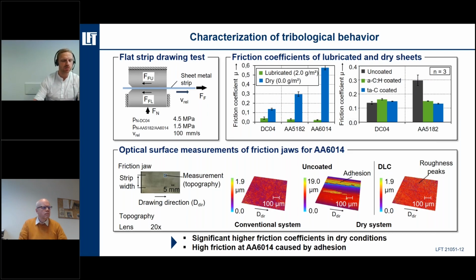we did some tribological tests in order to analyze the tribological performance of lubricated and unlubricated material compositions. For the characterization of the tribological behavior, the flat strip drawing test is commonly used to determine friction coefficients for deep drawing processes. Here in the upper left corner, you can see the basic principle of the applied test setup. The sheet metal, the blue line, which you can see here, is placed between two friction jaws. The lower jaw is moving upwards, applied with a defined normal force. While the strip is drawn through the jaws, a distinct drawing velocity was set up, and the resulting friction force could be measured according to Coulomb's law of friction.